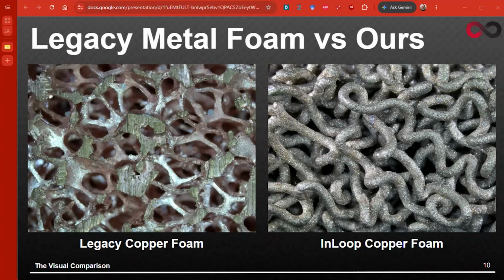Essentially, if there's any kind of temperature gradient, normally that means there's a differential shrinkage, which can cause a fracture. But because our material is able to either compress a little bit and extend a lot more than if it was solid or had straight links, it's actually much more tolerant to non-uniform shrinkage than our conventional lattice structures would be. Okay, yeah, that's really interesting. Thank you.